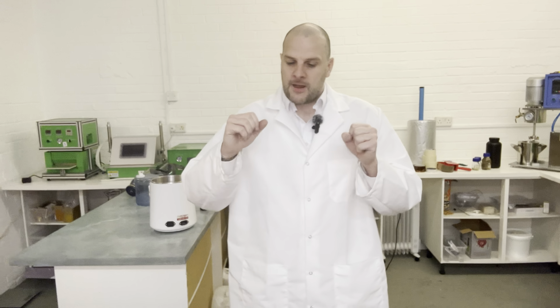And finally, we've done a scratch test. We took a pin, a weight of 100 grams. We dragged it across the panel of the one that did not contain graphene. It had a nice long scratch along the surface. However, when you compare that to the one that contained graphene, we performed it twice because the results were so good that the panel was unmarked by the pin and the weight of 100 grams. So I'm very, very happy with that, very excited, and hopefully you can see the benefits of just adding graphene.